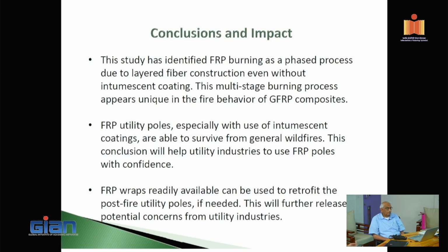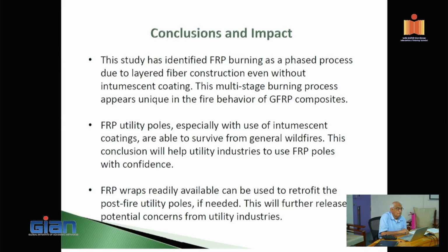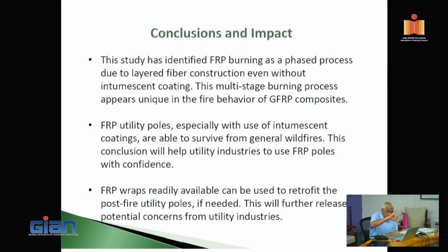So for 12-inch diameter of your utility pole, you just said that the cross section was half inch, right? Not cross section. Thickness is half inch. And it goes up to 120 feet high. No, I didn't say that. The 18 inch and 22 inch ones go up to 120 feet. Okay.